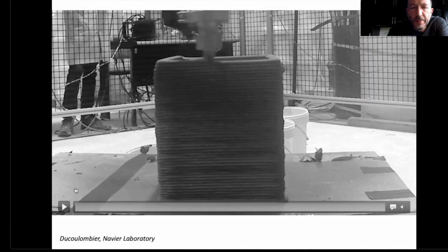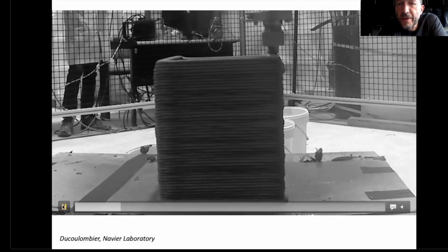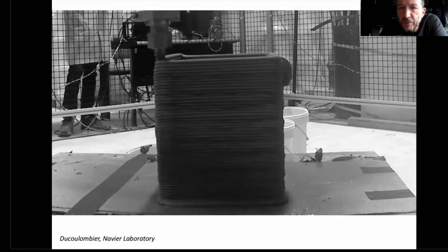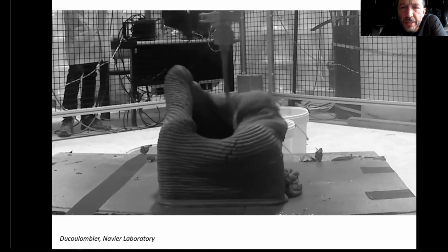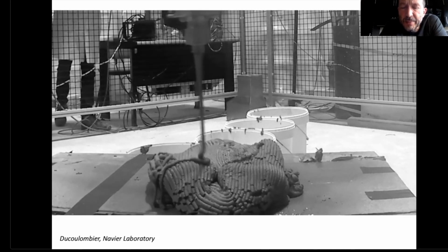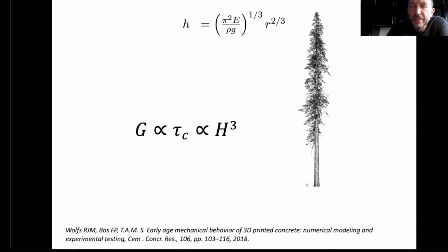And the other problem is that the main reason for failure during printing is not often a plastic failure of the first layer. It is often an elastic instability or so-called buckling of the entire object being printed. And this is called self-buckling. It is the same phenomenon as the one that dictates the maximum height of trees on this planet. And the particularity of this is that for the first time it prevents us from using this very basic relation between consistency and a typical length scale, because buckling involves the height of the object at the power 3 and not at the power 1.